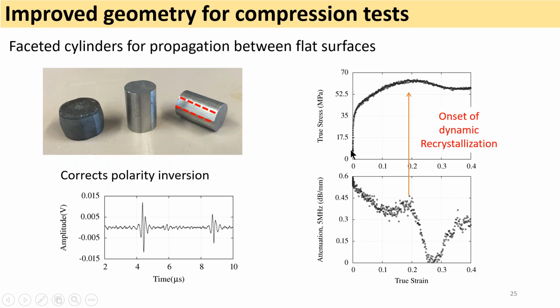Here in this figure, we can see a typical stress strain curve where we have an increase in stress as the strain increases, up until a moment where we see a decrease in the flow stress, corresponding to the moment where the recrystallization, occurring dynamically this time, starts to begin. What I have tried to do is take those waveforms, analyze the attenuation and plot it as a function of strain, to see if there would be some correspondence between the moment where we see a decrease in flow stress and the attenuation signal. What you can see here is that there is indeed a sharp decrease in the attenuation signal, which is for now very hard to interpret in terms of microstructure property, but at least it gives you an indication that this type of machine can actually give you an indication of the moment where the dynamic recrystallization occurs.